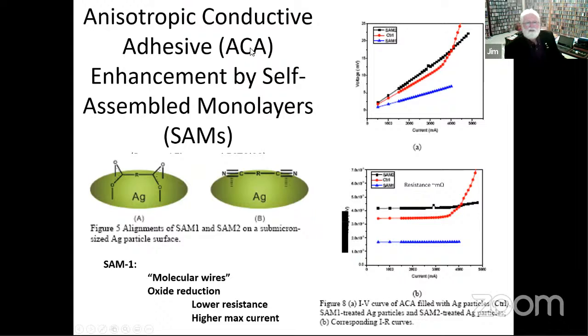So for the anisotropic conductive adhesives, a similar thing here. These are the silver particles in this case, not the usual thing for ACAs or anisotropic conductive films, but surface treatment, self-assembled monolayers can act as molecular wires and also provide some protection against oxidation, giving lower resistance and a higher maximum current. And here, these two are contrasted. This one stands, the molecule stands off the surface. Here, it hugs the surface. So this resistance result here is that with this one is actually for this, and the resistance goes up above the control resistance.